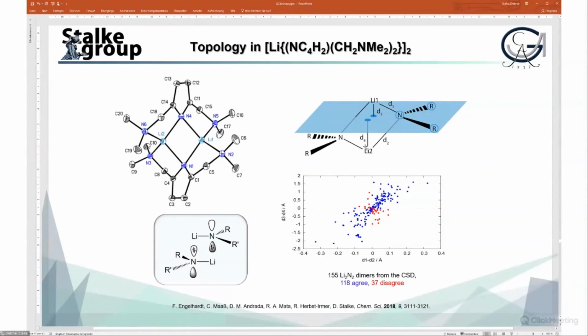If this is a minimum, then we have the scenario where both of them are in an arrangement where they cut the lithium nitrogen lithium angle in half, but they don't. They are in a stepwise arrangement, and that is true for 118 hits in the database, and that disagrees for 37.